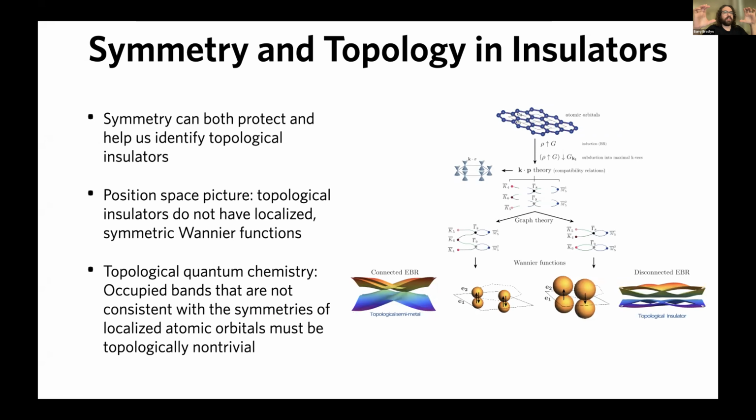But if you consider the occupied bands and some set of the unoccupied bands that they're band inverted with, so that you consider a set of bands that as a whole is topologically trivial, even though it's divided in half, then you can use Wannier90 to get Wannier functions that describe the occupied and the unoccupied bands just fine. So that's one possible subtlety.